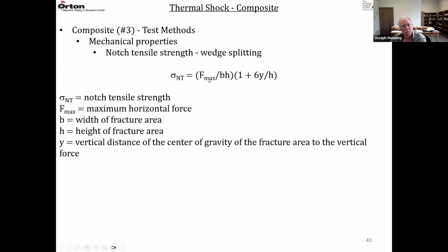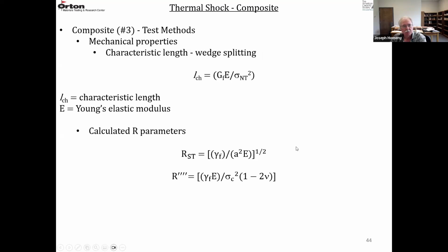F maximum, the maximum force. B and H are the sample dimensions. And Y is this vertical distance of the center of gravity of the fracture area to the application of the vertical force. And then again, LCH, the characteristic length, is GF times E over sigma NT squared. And that's basically your R4 prime parameter.